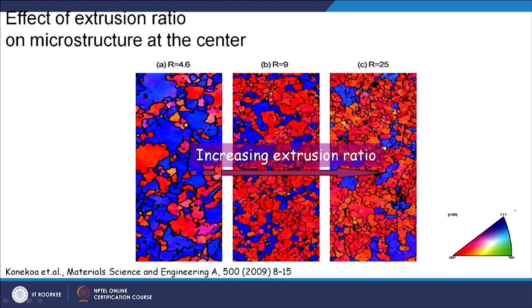So, a combination of 001 grains and 111 grains. And then as you are increasing the extrusion ratio, you can see the microstructure refinement which is taking place, and also you can see that the number of red color grains are increasing. So, that means you are introducing a texture also in the material, a crystallographic texture, which gives a predominantly one type of orientation to the grains.